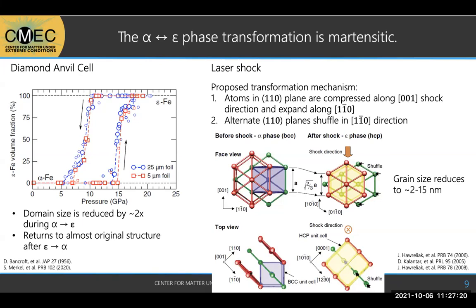First, you've got the atoms in this 110 plane, which are the green circles. And when you compress it along the shock direction, which in this image, you can see the arrow is pointing downwards, you end up compressing those green atoms, and then they end up expanding along the perpendicular axis. So you can imagine if you squeeze down on a foam or something, the axis along which you're squeezing compresses, but the opposite axis is going to start expanding. So that's what's happening. And that compression and expansion forms this kind of hexagon type shape.